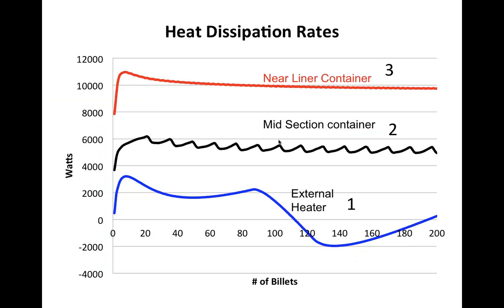When you combine these two, thermal temperature gradient and the thermal conductivity, you see right away which one is the winner. The red one, or design number 3. It has a very consistent heat dissipation rate compared to design number 1, when you heat it externally, and it fluctuates from positive to negative. And the other one, design number 2, fluctuates and has about half of the capacity to dissipate heat.